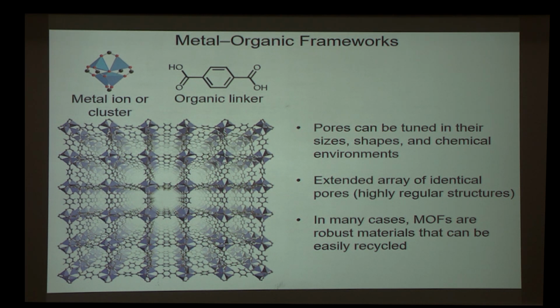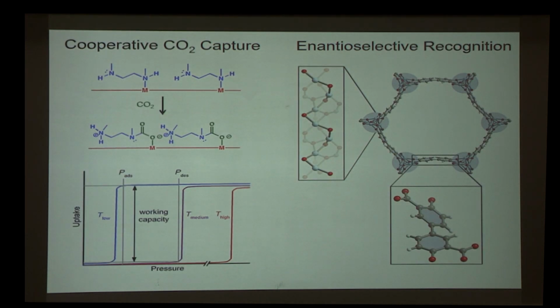And as I already mentioned, that pore environment is replicated indefinitely across the structure. So if we could find just the right pore environment to bind to a particular guest, we would have a very high density of active sites. Finally, in many cases, these materials are robust and they can be easily recycled. So there are many applications that we could think about pursuing with these materials, but what I will tell you about today is two specific problems that I've worked on. And I'll start by telling you about my work on CO2 capture.